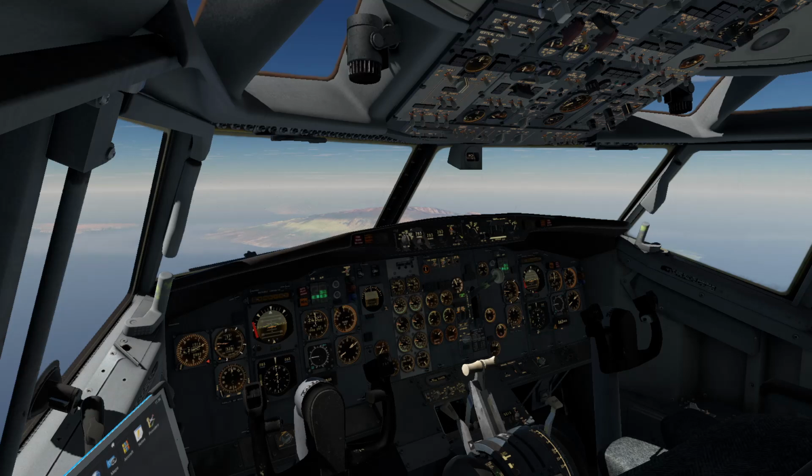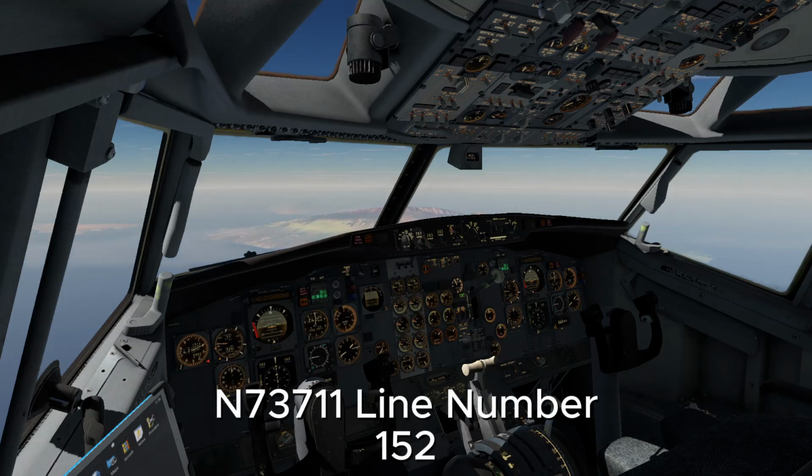Contributing to the accident were the failure of Aloha Airlines' management to supervise properly its maintenance force, the failure of the FAA to require Airworthiness Directive 87-21-08 inspection of all the lap joints proposed by Boeing Alert Service Bulletin SB 737-53A1039, and the lack of complete terminating action neither generated by Boeing nor required by the FAA after the discovery of early production difficulties in the Boeing 737 cold bond lap joint, which resulted in low bond durability, corrosion, and premature fatigue cracking.